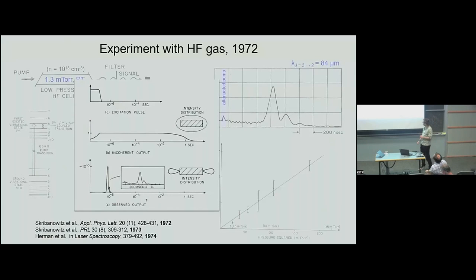It's directional, directed along the direction of the highest concentration of emitters. In this case, a cigar-shaped sample, so it's emitted at the ends of the cell. Some conditions or rules one can pick up from this experiment: all emitters should be identical, and any decoherent sources should be minimized, for example by low pressure.